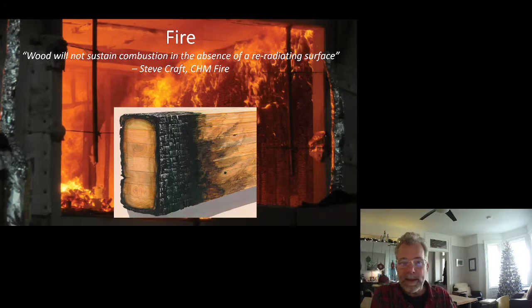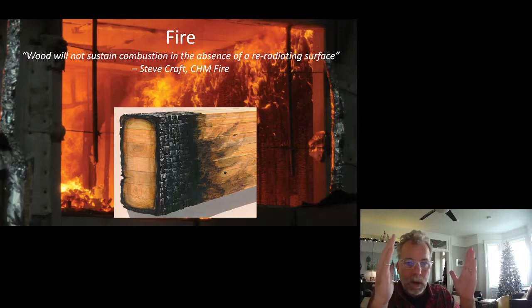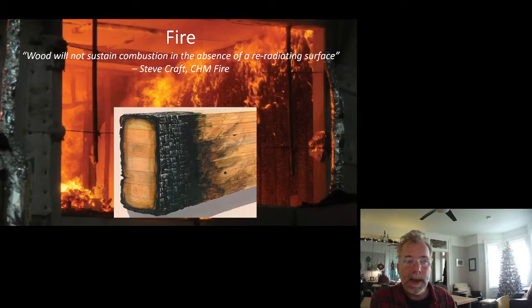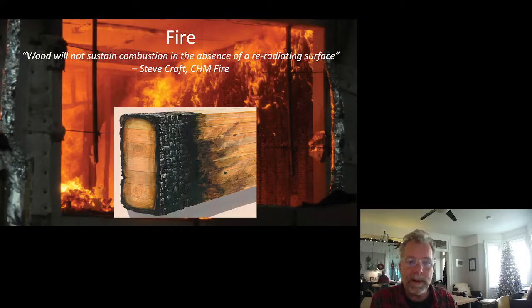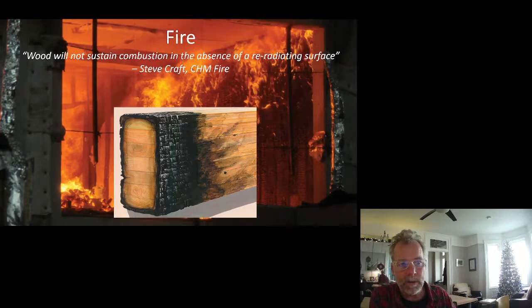So if we take a beam that starts at 200 by 300, after an hour that beam will be 118 by 218 — it will have lost 41 millimeters on all surfaces after an hour. If we neglect the strength contribution of the char, because it really has none, we wind up with a beam that's got some capacity left. That's how we design for fire — we add a sacrificial layer of wood all the way around the outside.